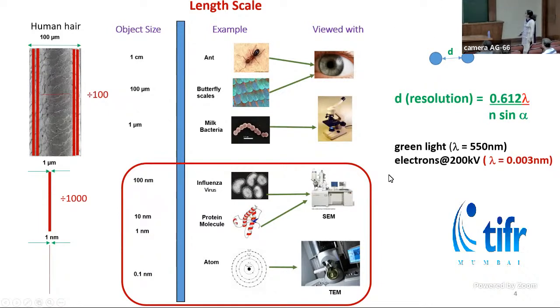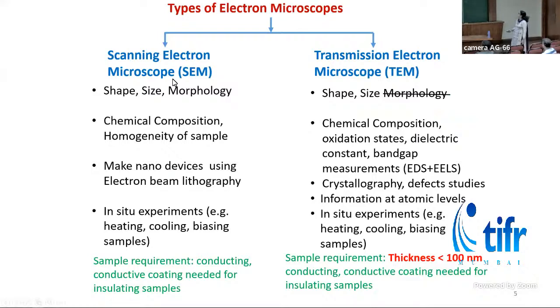If you use electron as a source of radiation and accelerate them at 200 keV, then the wavelength is 0.003 nanometer. That means we can view the objects of roughly around 0.0015 nanometer using electron microscopes. Basically, there are two types of electron microscopes, scanning electron microscope and transmission electron microscope.